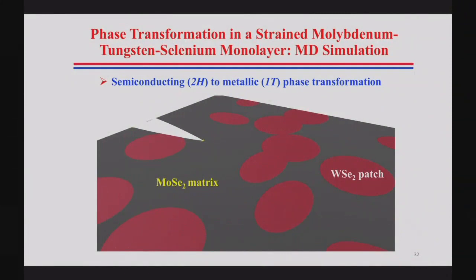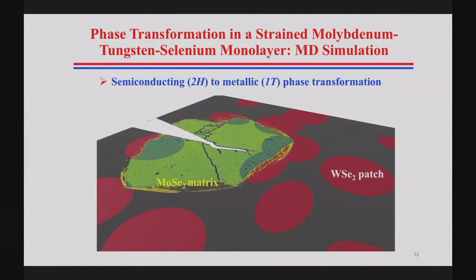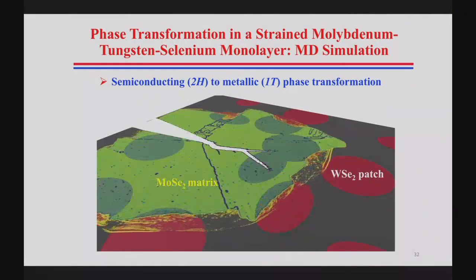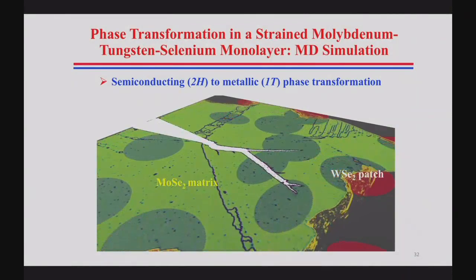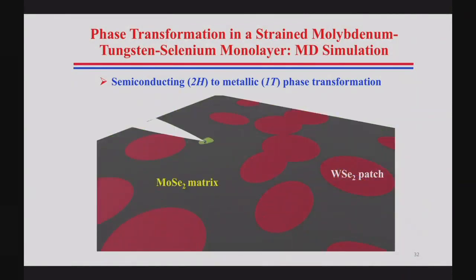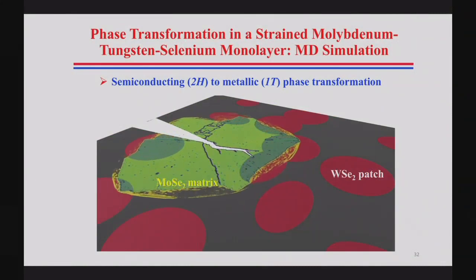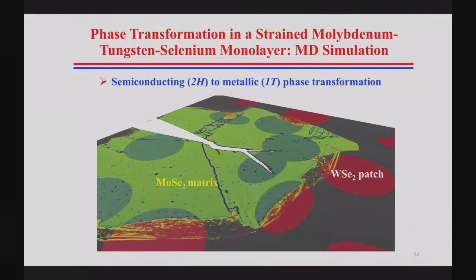Right. Okay. So this is a huge simulation. I will show you this movie, and when you see how the crack propagates, you will see the transition from 2H to 1T. The green region is 1T now. The rest of the matrix is 2H. And you can see very interesting branches taking place as the crack begins to propagate and so on. This is the stuff we want to model using machine learning.